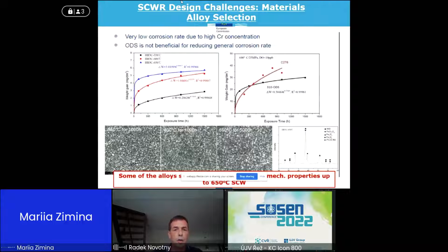If you look at the oxide layer, it is a very homogeneous, uniform oxide layer, even at high temperature supercritical water. On top of it, these alloys also showed acceptable mechanical properties up to 650 degrees C supercritical water. But here, as I mentioned, we definitely have a gap, because first of all, most of the exposures are short, in the range of 1,000, maximum 2,000 hours. We need longer exposures to extrapolate results to 20,000 hours of in-service life.